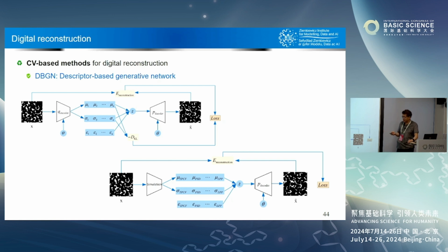This is another way to do that, a better way. Again, this is the standard VAE, same as we showed before. You start with the image, you take one encoder to convert the features into the so-called latent space. This is simply a vector, much shorter than the original image, and it's essentially the feature space, only understandable to computers, not explainable. And then you take it back to the image, where you have a loss function. Each time you try to minimize the loss function to make this closer to that one. So what we could do is, instead of using that latent space, the meaningless vector, as the feature space, we could use our descriptors as the latent space.